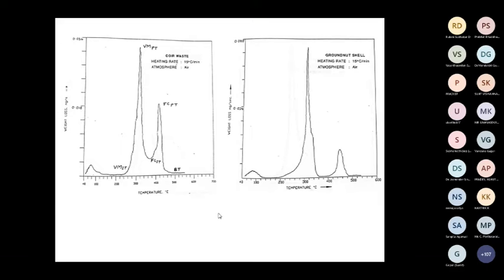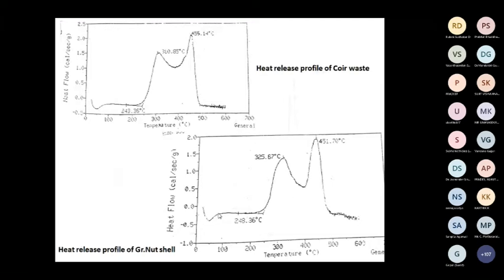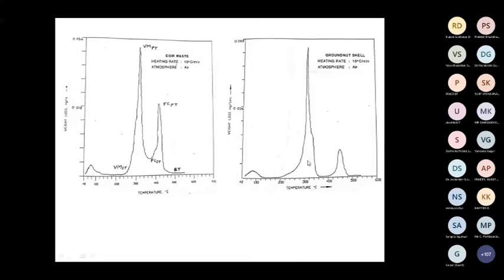This is for the TGA plots, for the same samples, coir waste and groundnut shell. Can you see the height of the peaks? This is the VM peak, heat release due to VM, and heat release due to fixed carbon. Fixed carbon peaks are higher than the volatile matter peak in DSC. Here also for DSC. Whereas in TGA, it is the other way around: VM peaks are higher than fixed carbon.